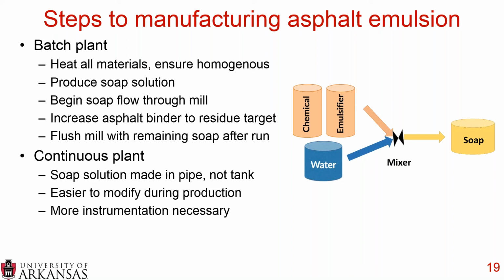And it's nice because you can modify things during production. If your asphalt emulsion isn't behaving quite as you'd like, you can tweak your chemical, you can tweak your emulsifier, and you can actually modify it as you're producing. However, it requires more instrumentation, a lot more meters. It's a little more expensive, but a lot of plants are moving in the direction of continuous plants. Historically, most have been batch plants. Regardless of if you're using a batch or a continuous plant, however, the meters and the pressure are absolutely critical. So you want to make sure that you're taking accurate temperatures, flow rates, and pressures, and then you are actually applying the proper pressure when you're making the asphalt emulsion.